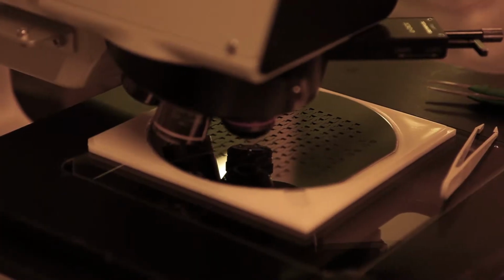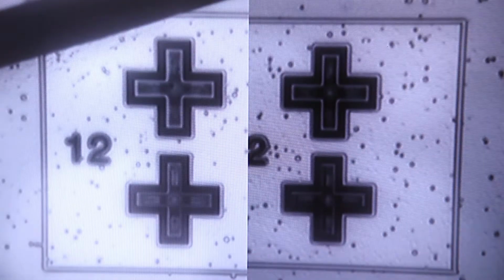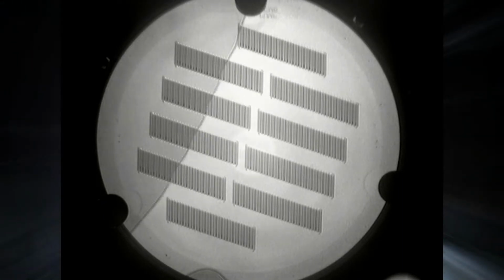Now that we have the 3 wafers with the critical features, we will use a fusion bonding process to produce a single monolithic silicon structure. First, all 3 wafers need to be aligned in relation to each other. A wave propagates through as the wafers come into intimate contact with each other, before going into a 1100 degrees Celsius furnace where the fusion will occur.